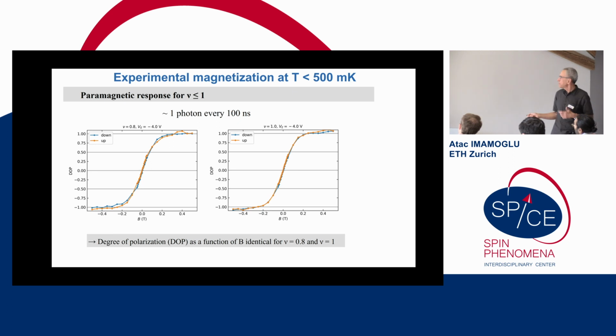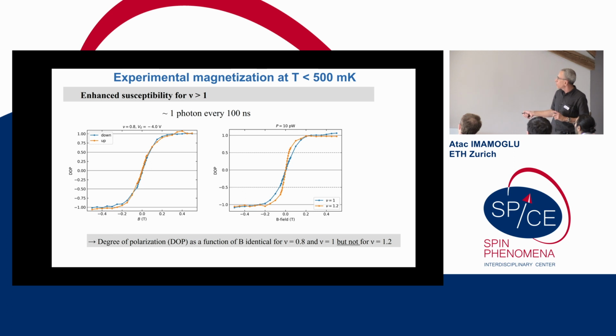Well, life is different. So basically what we saw, as we go to very low powers and the lowest temperatures we can reach, which is about 130 millikelvin, is that if you look at the magnetization at 0.8 filling or nu equals 1, it's identical. This spin susceptibility is very well described by a Curie-Weiss temperature that is less than 50 millikelvin, and we don't know the exact number because of our error bars. Okay, things are different though. If you go to nu equals 1.2, then you can see this clear sharp increase of the spin susceptibility, indicating ferromagnetic correlations.